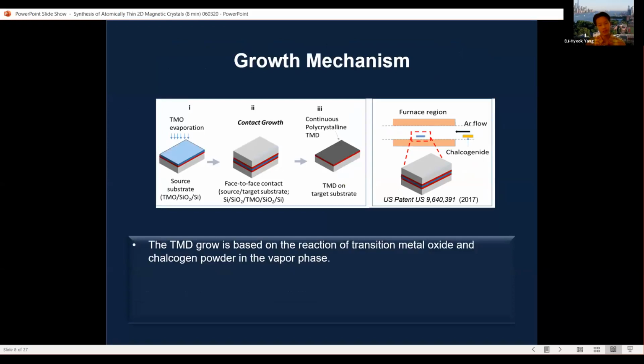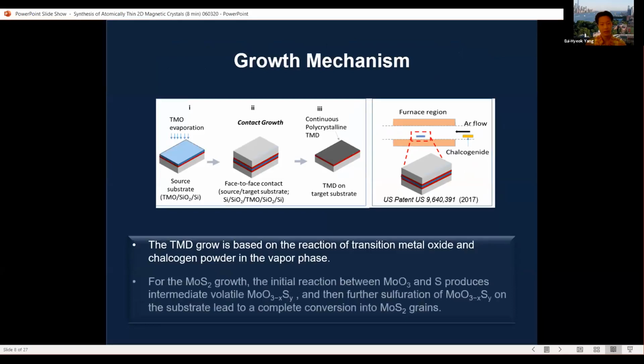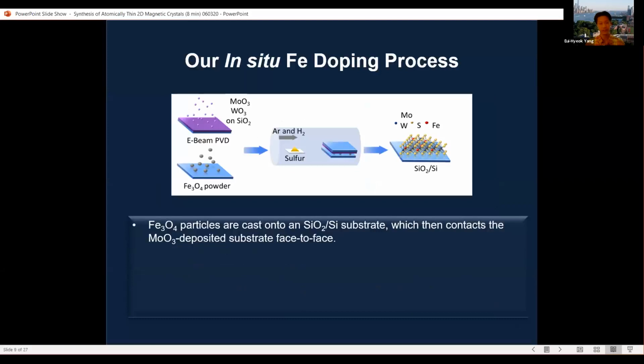So to synthesize the material, we rely on the reaction of transition metal oxide and chalcogen powder in a vapor phase. Specifically for molybdenum sulfide growth, the initial reaction between the transition metal oxide and the chalcogen atoms produces an intermediate volatile suboxide, which then, through further sulfurization, makes the complete conversion into molybdenum sulfide grains, creating these monolayers and bilayers based on your target.